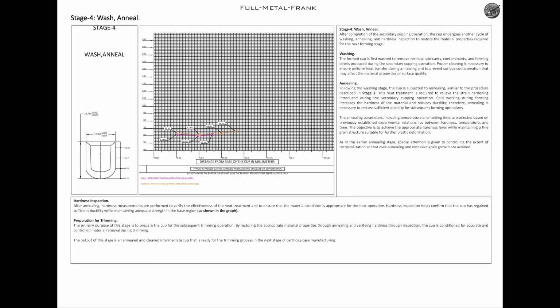Stage 4. Wash anneal. After completion of the secondary cupping operation, the cup undergoes another cycle of washing, annealing, and hardness inspection to restore the material properties required for the next forming stage. Washing. The form cup is first washed to remove residual lubricants, contaminants, and forming debris produced during the secondary cupping operation. Proper cleaning is necessary to ensure uniform heat transfer during annealing and to prevent surface contamination that may affect the material properties or surface quality.